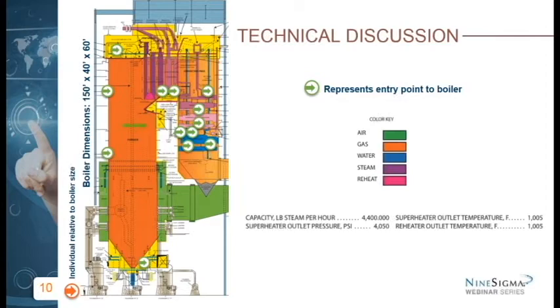So as these walls thin, they can get to the point where they spring a leak, basically. And that leak could either be water or steam, depending on where you are within the circuitry. And that requires us to shut the unit down to go in and repair that leak. And if the leak is over on the right side where you see all the green arrows, those are entry points. Typically, those are not too difficult to get to. The challenge there is the heat, because these surfaces are all running up over 1,000 degrees.